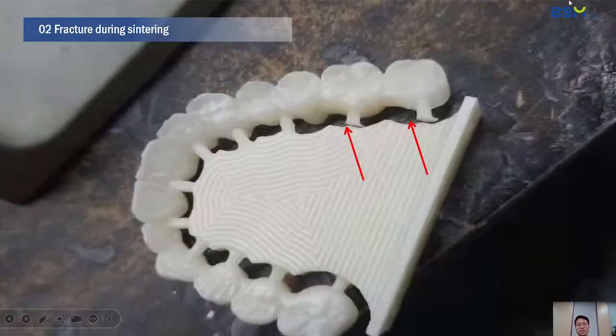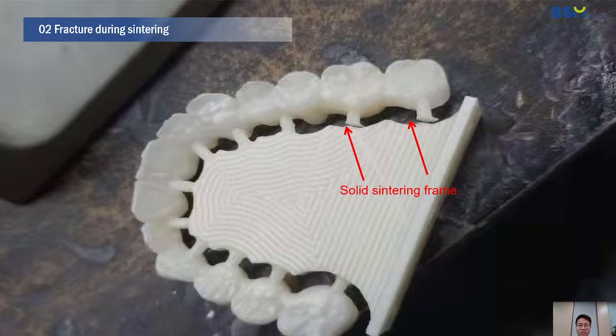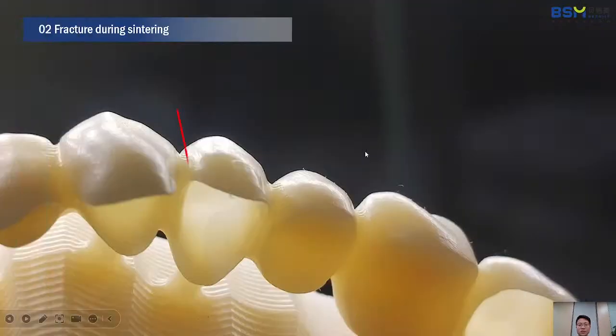For example, for this case, we checked and found the sintering frame is not so good. We can see it's a solid sintering frame, and because it's a solid part, the thickness has a bigger difference from our restoration. So during sintering, the shrinkage is very different for those two parts, and here is some stress concentration and the connector cracked from here. And for this kind of case, we checked the sintering program and found the heating rate and cooling rate are very fast. It's not the sintering program for long bridges, it's a normal sintering program. So we need to lower the heating rate and cooling rate for this kind of crack.